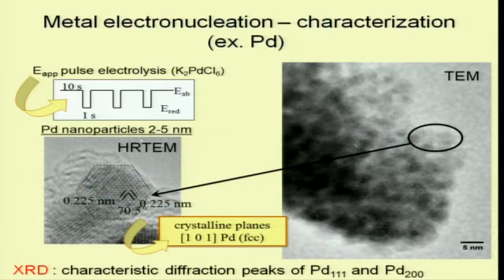In fact, the tricky thing to obtain nanoparticles is that it's necessary to use a pulse strategy. Pulse electrolysis, for instance, this one, you apply a potential for 1 second.